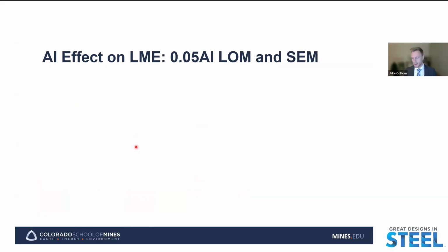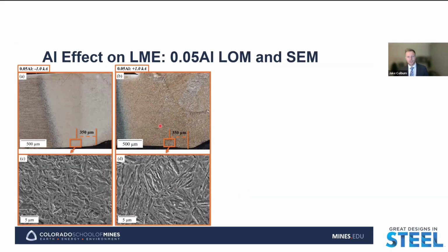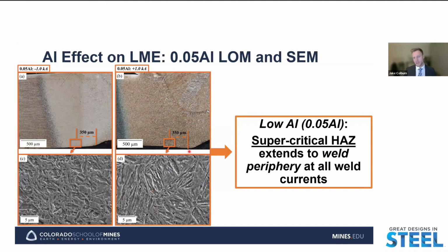And then if we're interested in taking a look at the cross-section of these welds, here we have the low aluminum alloy welded at 1 kiloamp below and above its expulsion current. And we see here a cross-section of the weld with the weld shoulder and weld periphery, these optical micrographs where the substrate was etched with 2% nital. And so what we see here is that even 350 microns into the weld periphery, we still see what we could describe as the supercritical heat affected zone in this region, to where the microstructure is a mostly martensitic microstructure with potentially still some bainite, at this lower current.